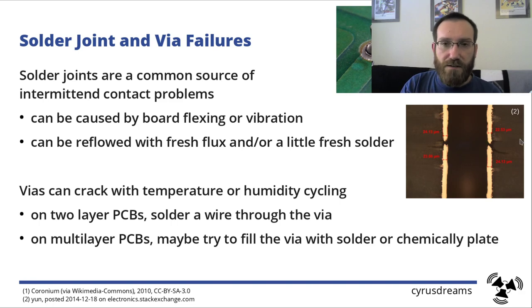It might be cracked solder joints. If you have a two-layer PCB, you can fix that relatively easily. You stick a wire through there and then solder it to the top side and the bottom side, and the via is replaced by your wire. If you have a multi-layer PCB, where also in the middle there are some connections, it's harder to do that because you don't know if the solder will flow alongside the wire down there. But you can try that.